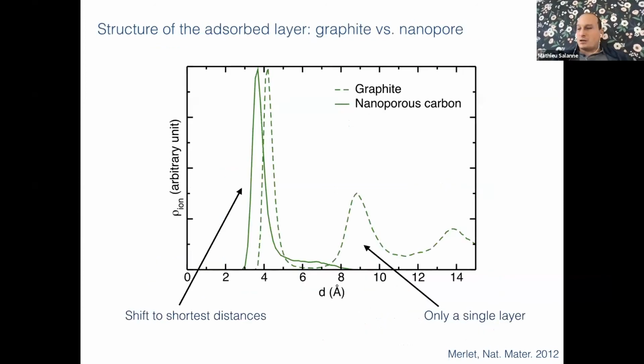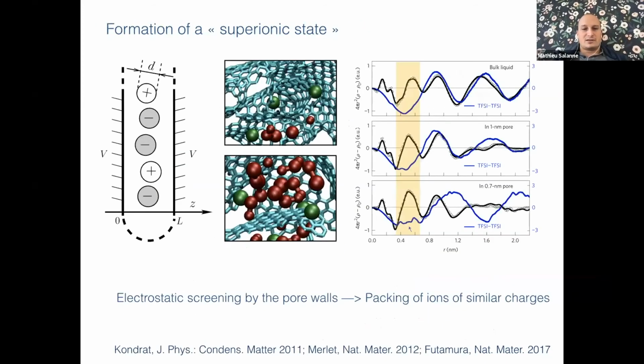I think an interesting story about all this is that since the experiments in 2006 by the groups of Gogotsi and Simon, a lot of people have started to understand why these nanoporous carbons were giving increased capacitance. And I think this is a nice story about first a theoretical model, which was proposed by Kornyshev in 2011. It's the picture on the left here, in which his theory was that due to the screening by the pore walls and the strong confinement, you end up with a structure in which anions, for example, that normally would repel each other, so in the liquid you don't expect them to be in contact.